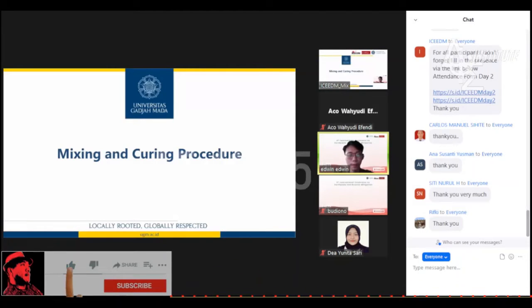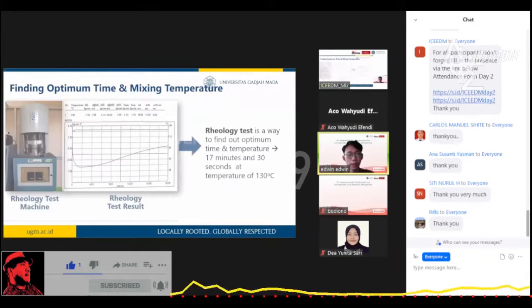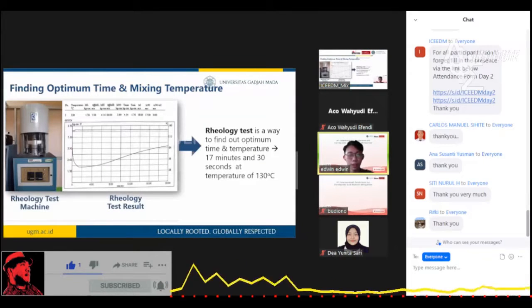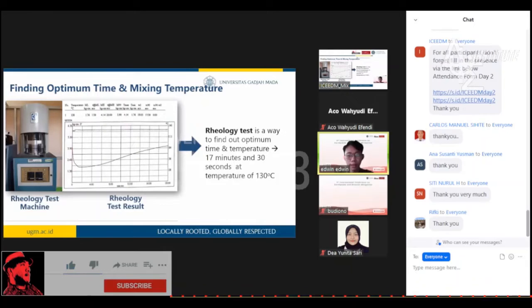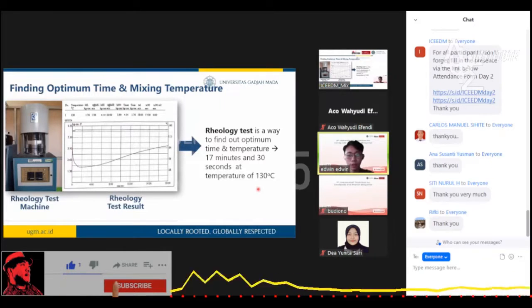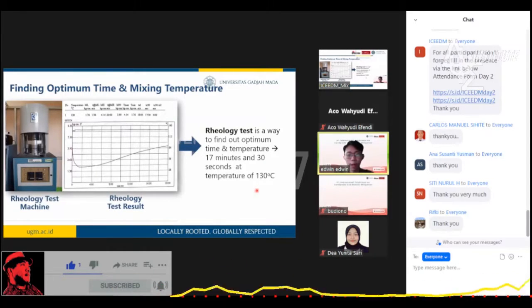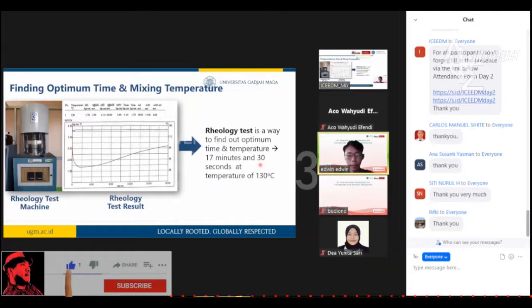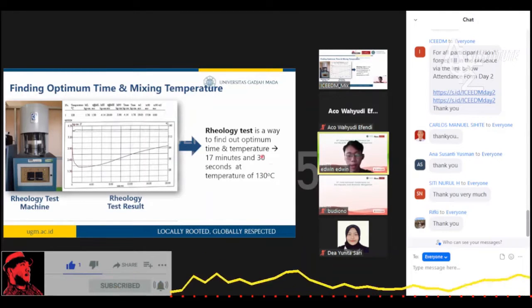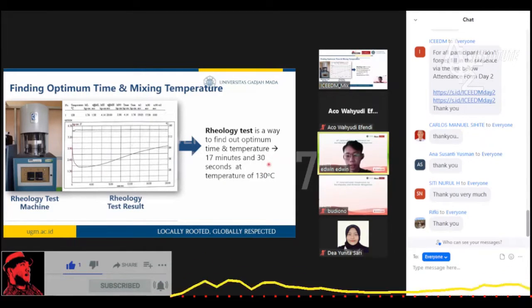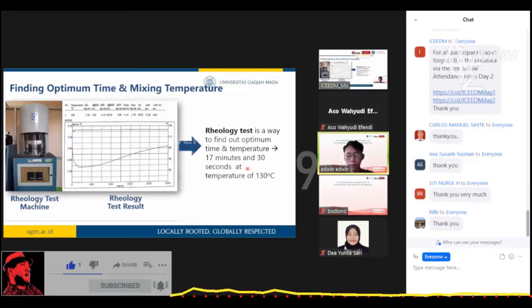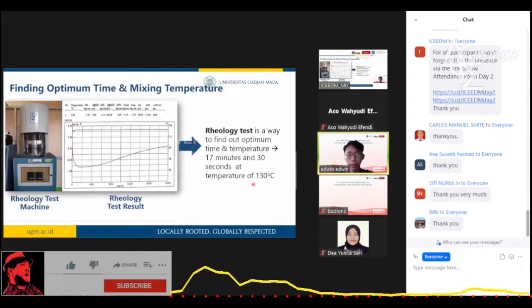Next is mixing and curing procedure. The first step for mixing and curing procedure was rheology test. Rheology test was used to find optimum time and temperature for the vulcanization process of rubber. And from the rheology test, it was found that the optimum time was 17 minutes and 30 seconds with optimum temperature of 130 centigrade.